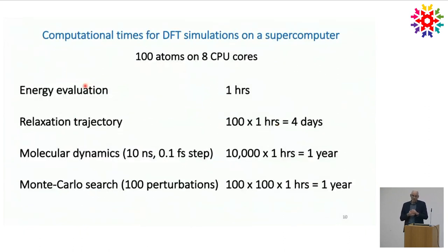Now, there are some considerations here, because if you are going to solve something that hasn't been solved yet, like now I just showed the tin oxide surface that has now been solved, but the other outstanding problems out there, you probably need about 100 atoms. If it's a bulk material, you need to describe a chunk of your bulk and then the defect you're interested in or whatever. If it's a surface, you need to describe sufficiently many layers of a slab model of your surface, sufficiently many layers that it's behaving like a surface and not like a thin film.